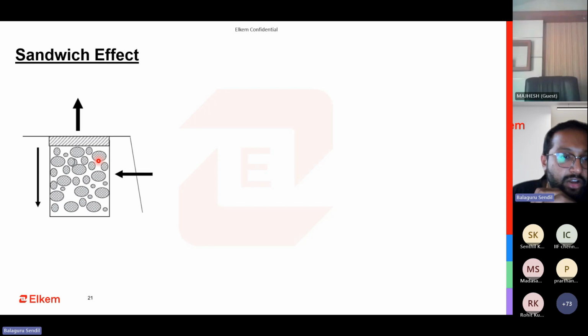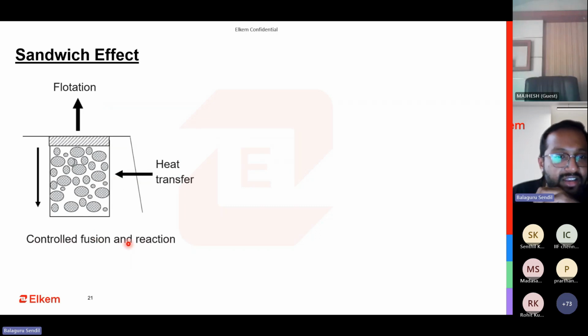So what happens here is that you have put the FSM here and you have put a cover on top. So it has this flotation point. The metal comes and the entire thing will float up. The other one is the heat transfer. The third one is the control, fusion and reaction. These are the three things that will happen when your liquid metal gets exposed to the pocket. So it will definitely float up to the top. Before that happens, you have a heat transfer happening because the side wall of the pocket will get heated from the metal, and the heat transfer starts to fuse the FSM that is inside here and the reaction starts to happen.